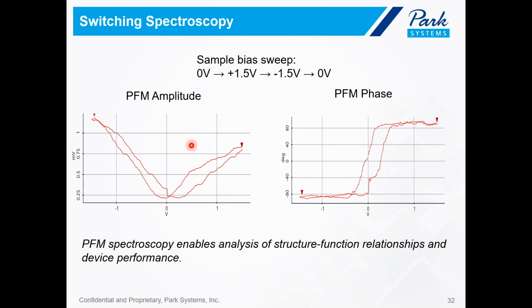So on the left, we have the PFM amplitude response. Since the PFM amplitude directly measures displacement of the sample, the strain response as a function of the sample bias can be measured in a specific piezoelectric domain. And this curve has a characteristic butterfly shape for piezoelectric materials. In addition, we can learn the coercive voltage from the curve. It's about 0.3 volt. On the right-hand side, we have the phase hysteresis loop, which is a typical response of the ferroelectric material. So in conclusion, the PFM spectroscopy enables analysis of structure-function relationships and device performance assessments.